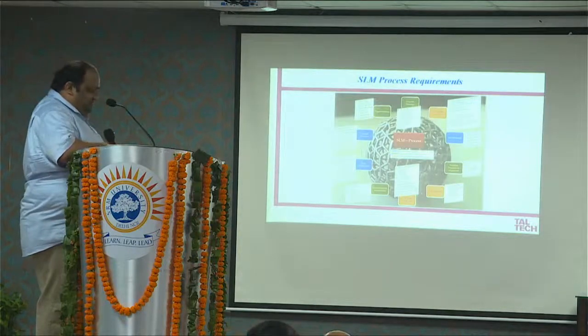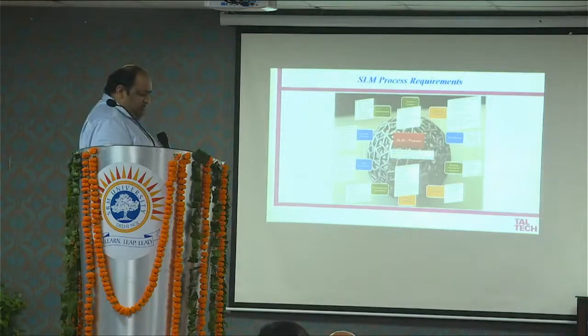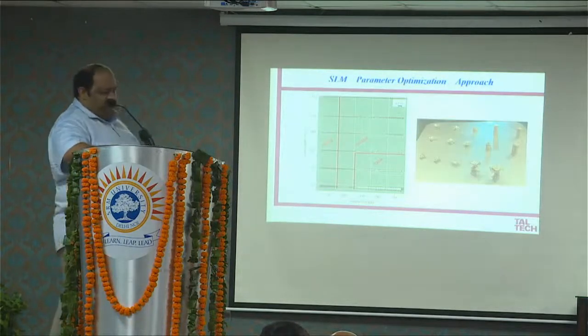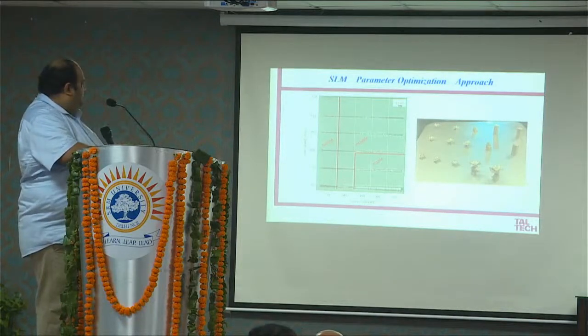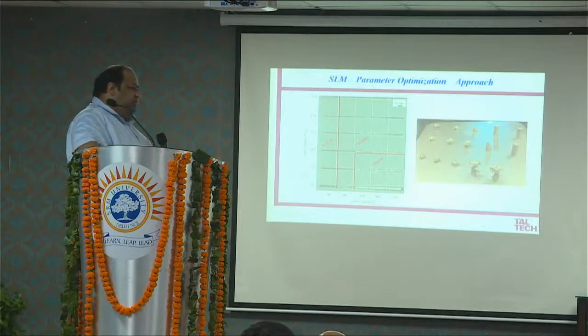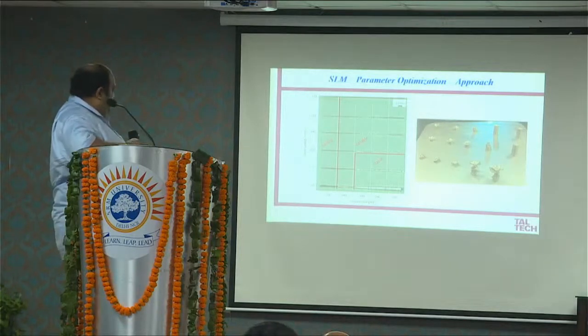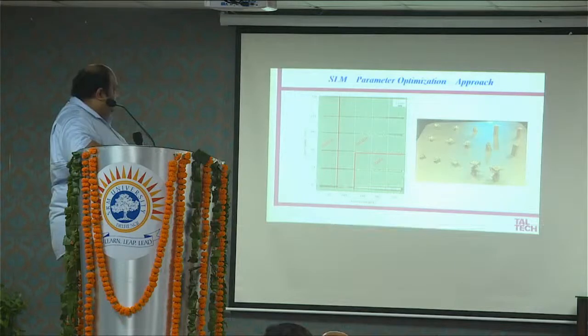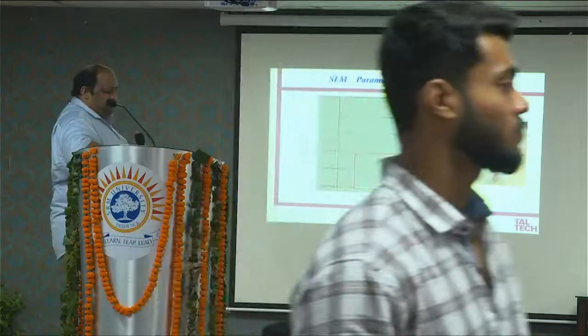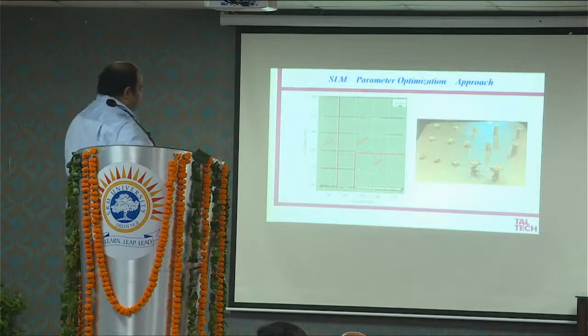There are a lot of parameters which affect this. I'm not going into the details of these parameters because they are quite extensive, but I just wanted to show that, similar to any welding approach, you can select the process parameters with a combination of laser speed, laser power, and other laser parameters, and see where you have a very good melt pool, and depending on that, you can narrow down the process parameters. If your process parameters are not correct, you may not get the intended shape of the specimen. Either the energy might be too little to build the specimen, or the energy will be too high, so that you will have cracking in the specimen. So you need to optimize in such a way that the melt pool has sufficient strength and sufficient dimensions so that you will be able to produce your samples without any restrictions.